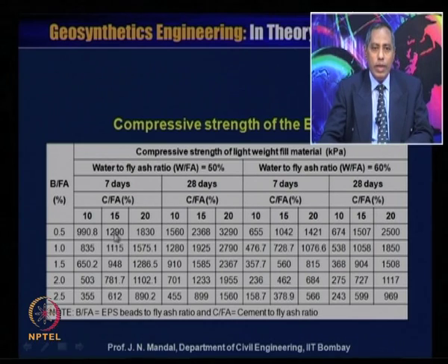And when the cement to fly ash ratio is 15% and beads to fly ash ratio 0.5%, the compressive strength value is 1290.